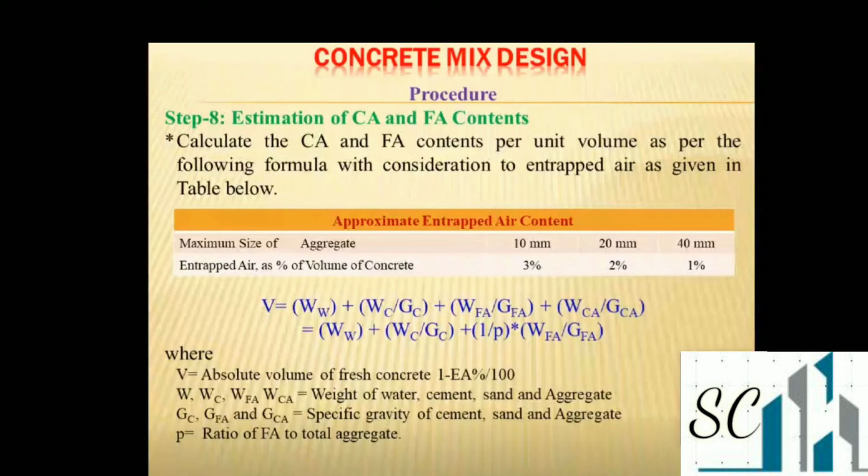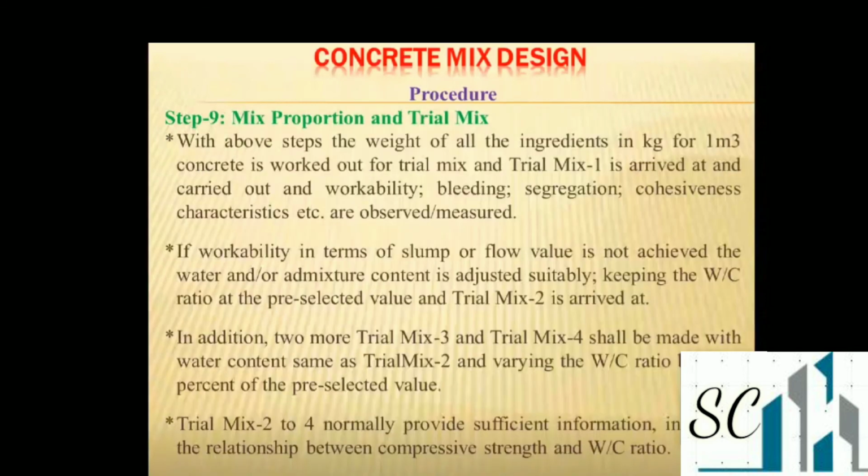Step 8 is the estimation of coarse aggregate and fine aggregate contents. Depending upon the maximum size of aggregate, we will be able to get the approximate entrapped air content. For 10, 20 and 40 mm, it is 3, 2 and 1% respectively.